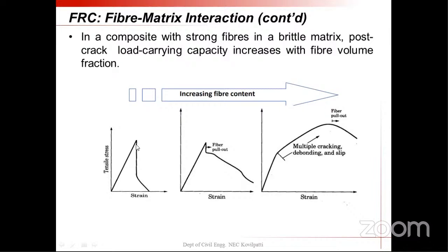Once it reaches the peak stress, there is a sudden drop. There won't be any possibility of taking the stress. And the second case is the strain softening case. You can see once it reaches the peak stress, after that the strain is increasing, but there won't be any increase in stress. It is decreasing. This second curve is called strain softening, and the third one is called high performance FRC.